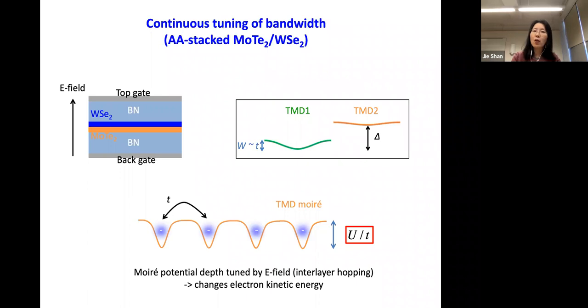And partly, as I mentioned, the Mott transition is still kind of a mystery to us. From an experimental point of view, it's not easy to study because it's not easy to find a system where you can tune the relative importance of interaction, U over t. Often, people use doping to change that, but when you change doping, you can get into defects, because you need to reduce the density quite a lot. So you get into the limit of how clean your sample is, this and that.